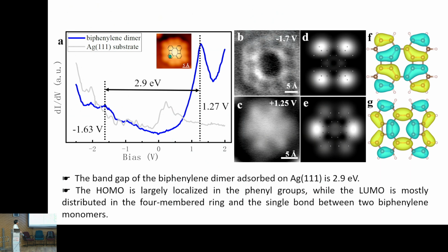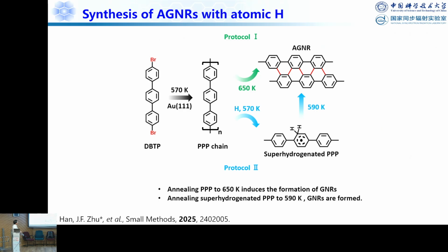Okay, and we also further analyze the STS spectra to find out this band gap is like 2.9 eV. And actually if you do this at the HOMO position, if you put this mapping, you can see the electronic structure which is like this, and then the DFT calculation is consistent with our result. Okay, so this is the graphene nanoribbon.